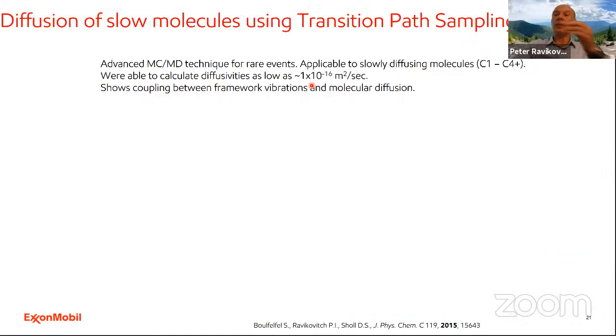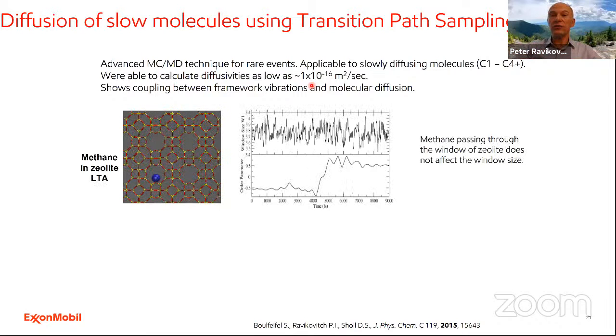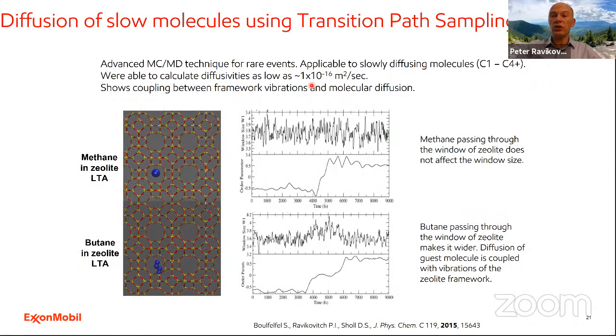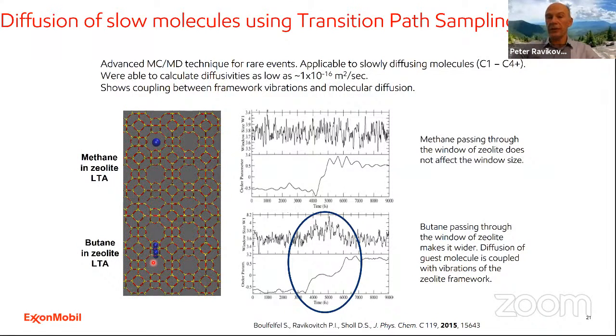However, if the molecules are larger, what can happen is that these molecules can actually expand the zeolite or other porous material during diffusion. And you can see it very nicely here. These are simulations performed also in David Scholl's group using so-called transition path sampling. What is shown here is methane diffusion in LTA zeolite, which passes quickly through the 8-member ring window, and butane diffusion through the 8-member ring window of zeolite LTA.